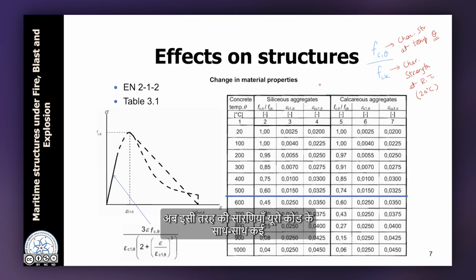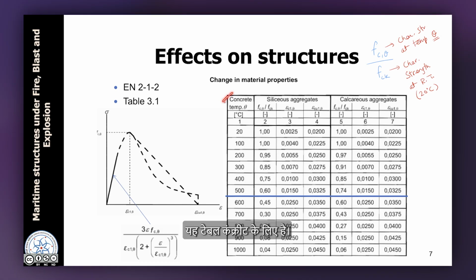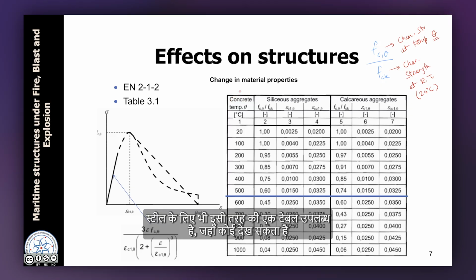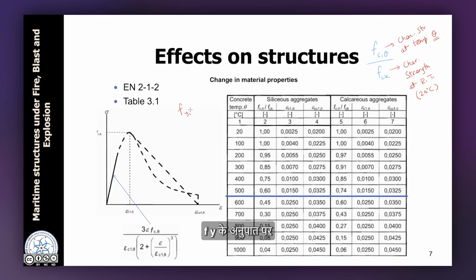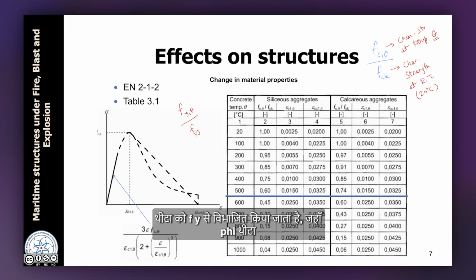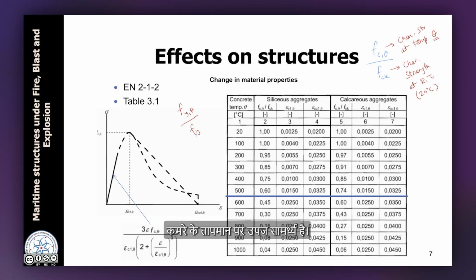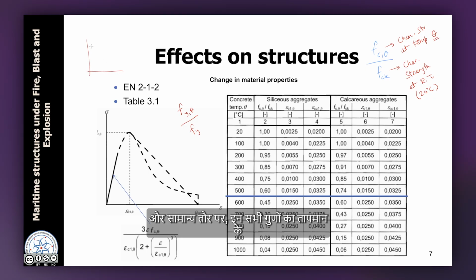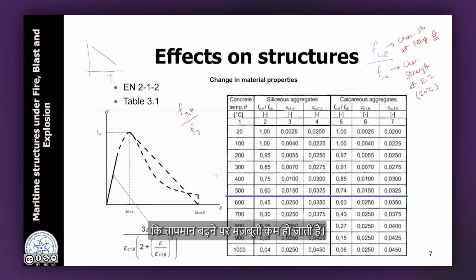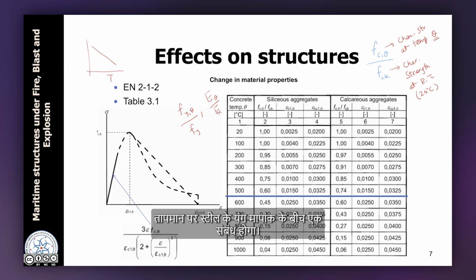Now similar tables are available in Eurocodes as well as in several building codes and also in several textbooks. This table is for concrete. A similar table is available for steel, where one can look at the ratio of Fy theta divided by Fy, where Fy theta is the yield strength at a temperature theta, whereas Fy is the yield strength at room temperature. In general, all of these properties have a decreasing correlation with temperature, which is that when temperature increases, the strength reduces. Similarly, there will be a relation between E theta divided by E, which is Young's modulus of steel at a temperature theta divided by Young's modulus of steel at 20 degrees Celsius or room temperature. So all of these properties follow a trend like this, where with increasing temperature, the amount of property decreases.